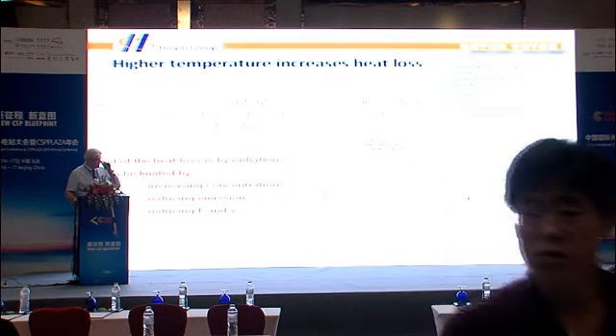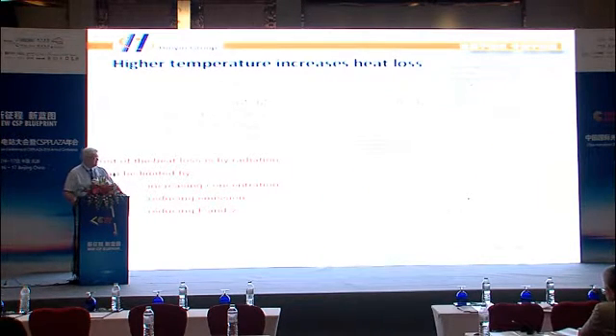You see here for one of our tubes the heat loss. So at 400 degrees we have a little bit more than 200. I think it's something like 220 watts per meter heat loss. So if we look at it, there are a lot of things that we can do. We can lower the emissivity by new coatings, but we can also increase the concentration ratio.